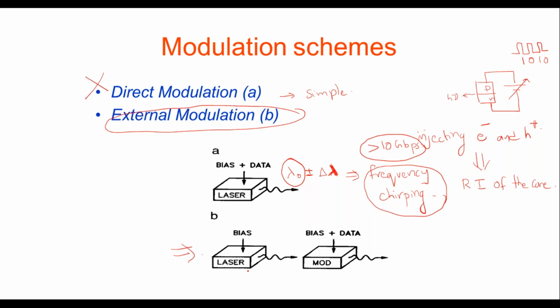In this case, the laser diode is always kept at a fixed bias. A fixed bias means you always keep the laser diode on. So the laser is always on. Rather, what you do is you put an external device which is called a modulator. Probably this is made out of III-V based material, or this could be made out of lithium niobate material. It could be made out of one of these, and you would change the property of this modulator so that at the output you would receive either a 1 or a 0.